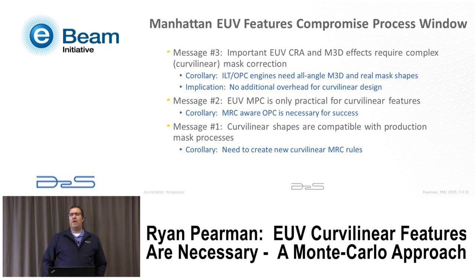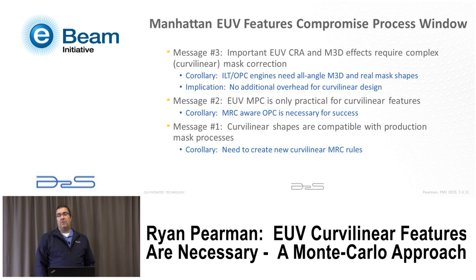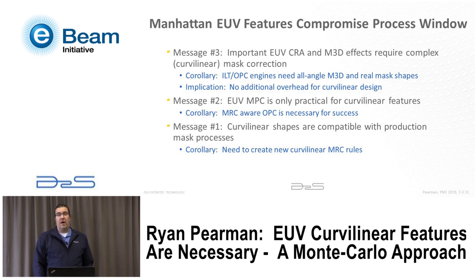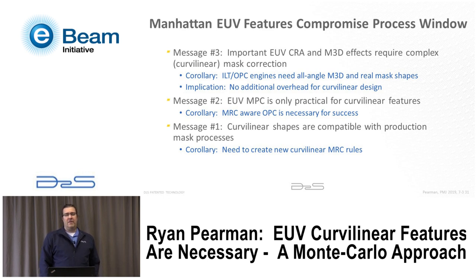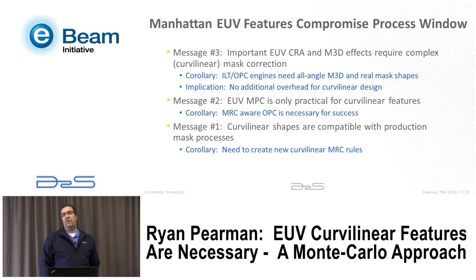The third message: the complications of chief ray angle and mask 3D effects create non-equivalences between the curvilinear and rectilinear solution. If we need to use curvilinear solutions, our OPC tools need rigorous M3D all-angle solvers — otherwise the mask effects will be wrong and we won't get the right answer. By making OPC engines purely curvilinear, that is one step closer to the goal of having curvilinear design with no additional overhead, removing one barrier.